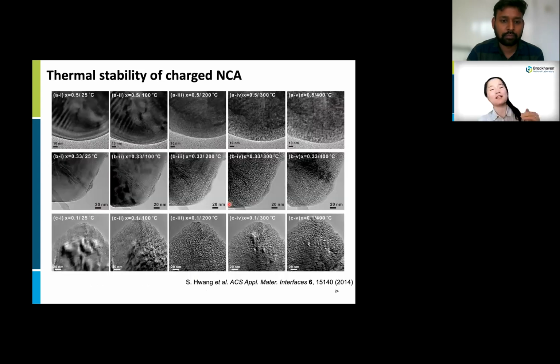Inside the TEM, I heated charged NCA particles to see their thermal stability, where the remaining X means the remaining lithium amount. As the remaining lithium becomes less, the material becomes porous at a much lower temperature, which means oxygen gas is released with phase transformation. Oxygen gas evolution is a really bad event because it can react with the flammable electrolyte inside the battery, and in the worst case, a catastrophic explosion can happen. And in the overcharged sample, we see porosity evolution at 100 degrees C, which is a low enough temperature we can reach in summer.